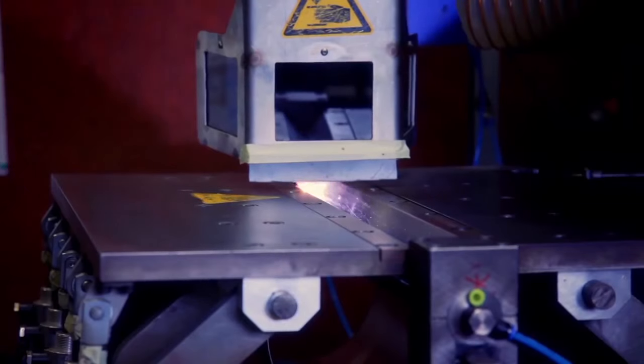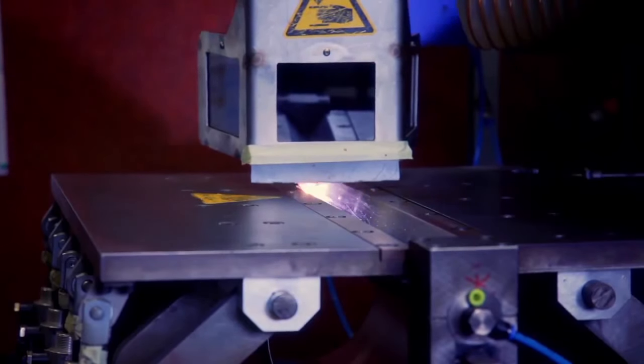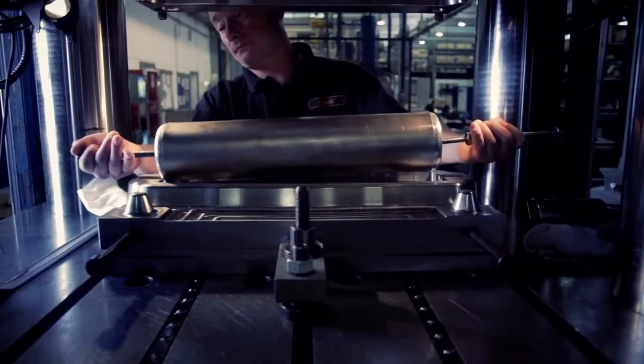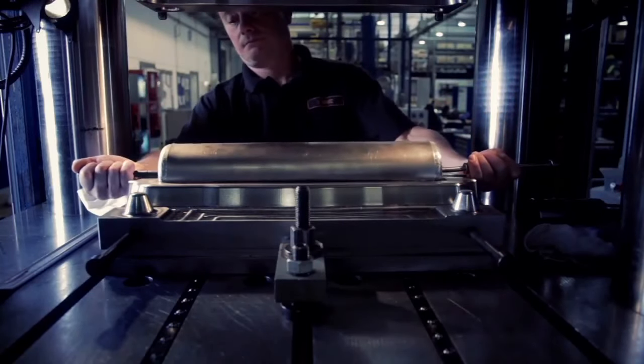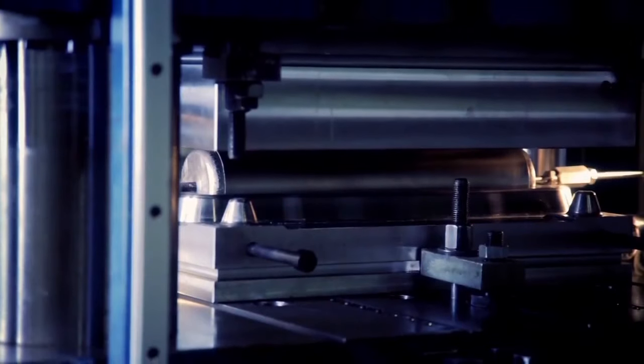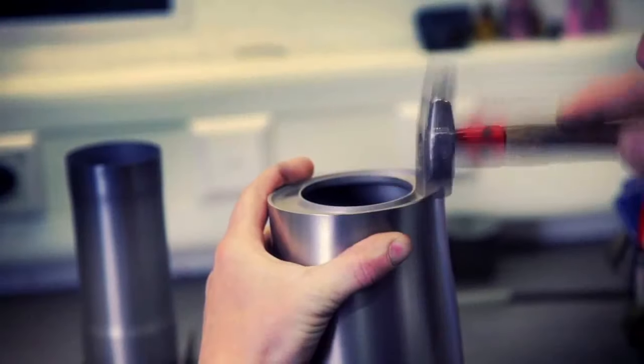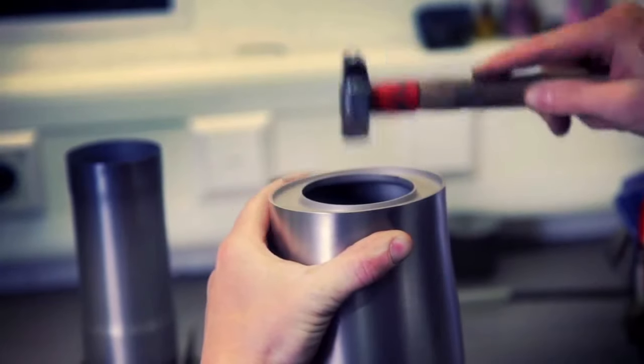A specific grade of titanium alloy sheet is chosen to be bent and laser welded to form a tube. To create the distinctive elliptical shape of the Huayra's muffler, the tube is positioned in a large hydro tool where high-pressure liquid makes it expand into the mold.